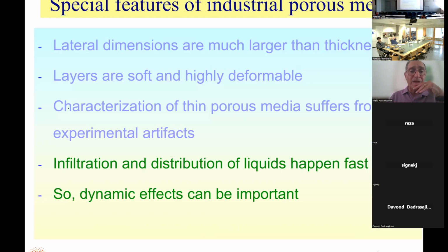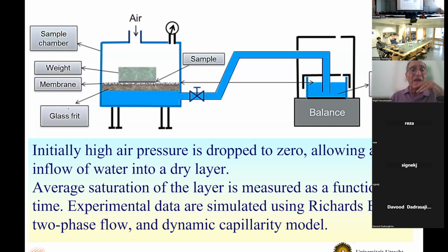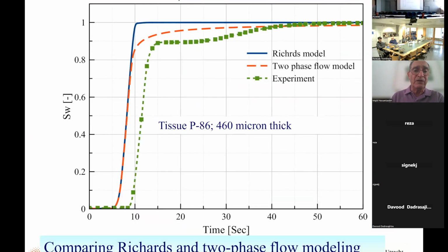And so we did that experiment in the same setup. As I said, we can start with a dry sample and with a very high air pressure, and then reduce the air pressure. Now, if you do it in small increments, you get the typical capillary pressure saturation curves. But in one experiment, we decreased the air pressure drastically so that the layer could get wet in a very short time, as happens. And then the data are like this, the green. As you can see, in a very short time, it goes to some large value and then almost a flat plateau. So now you should be able to simulate this.